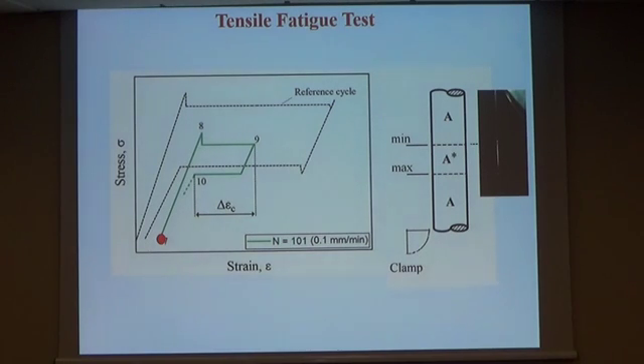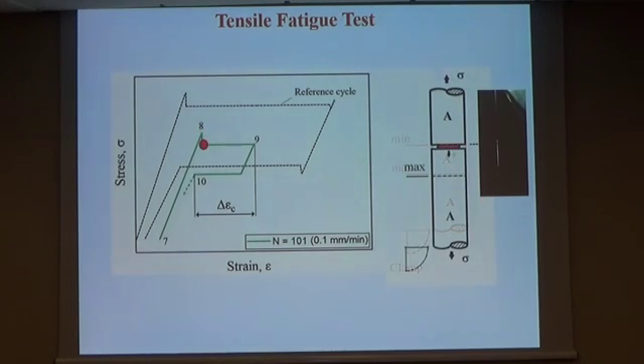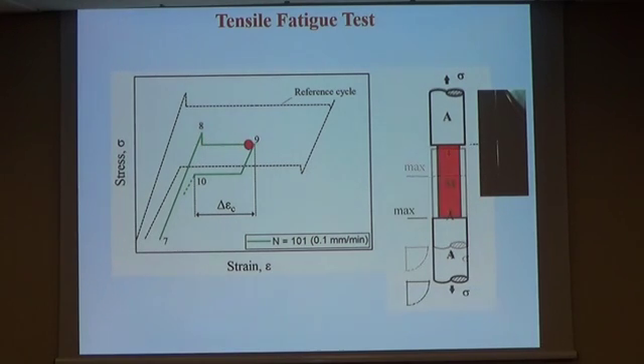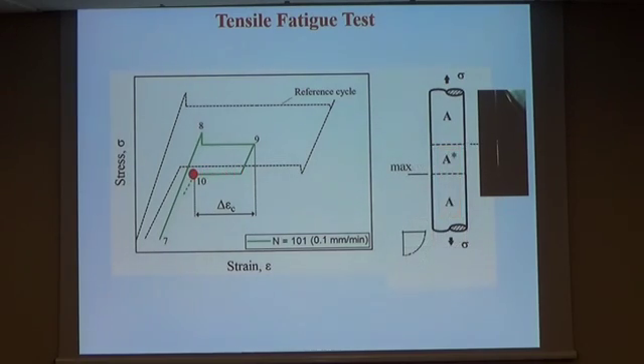Later we can increase the strain rate, maybe by one order of magnitude or something like that. We continue checking this point. Just to be sure, we can apply one cycle with the same strain range, so the transformation domain nucleates without problems and we proceed cycling. We can continue cycling in this region.